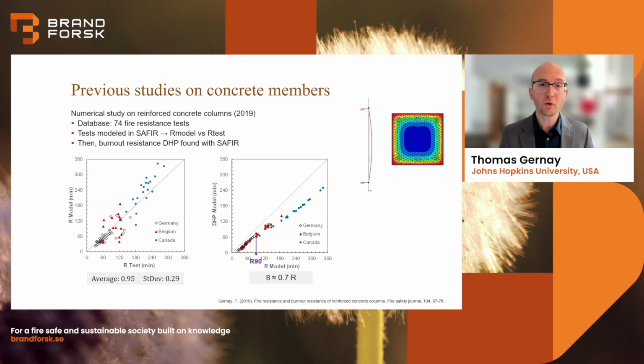It means that the reinforced concrete columns with a fire resistance of 90 minutes would survive a fire that lasts for 63 minutes or less until the very end of the fire event. But if the fire lasts longer than 63 minutes, the column would eventually fail during or after the cooling phase. The thermal exposure would have been such that the column has been damaged to such an extent that it will not survive indefinitely.